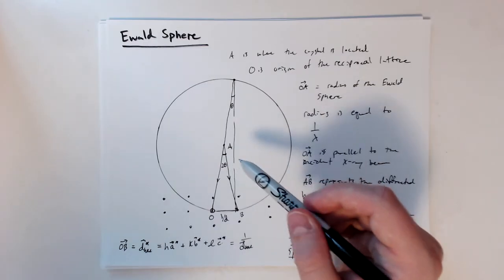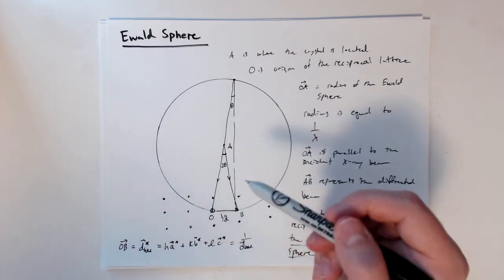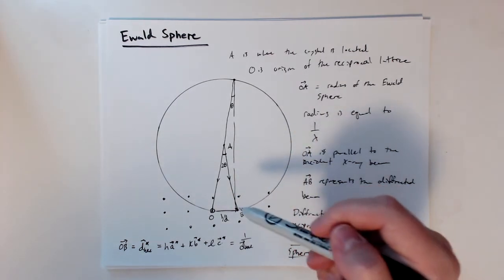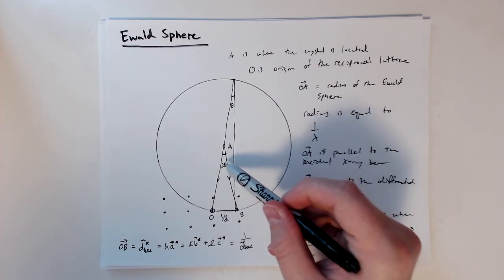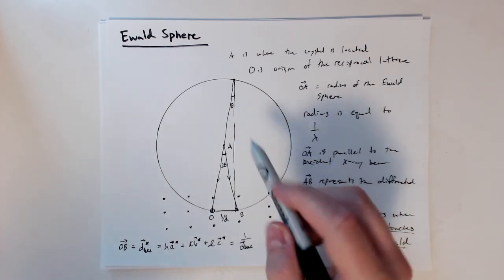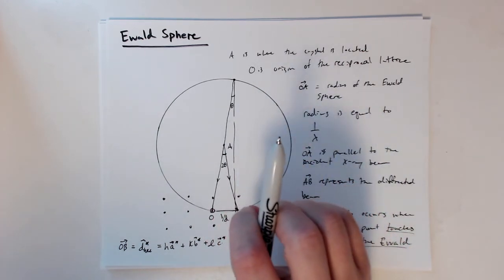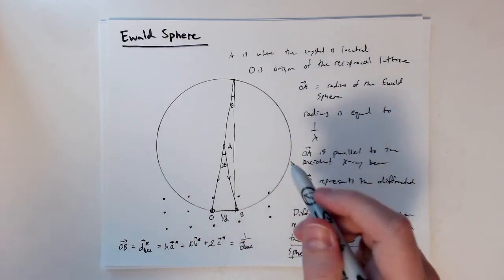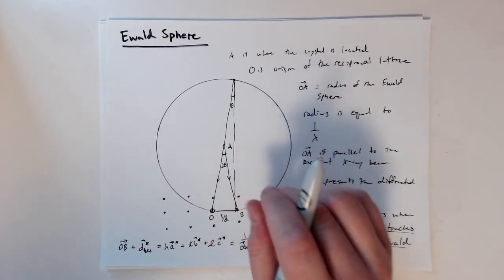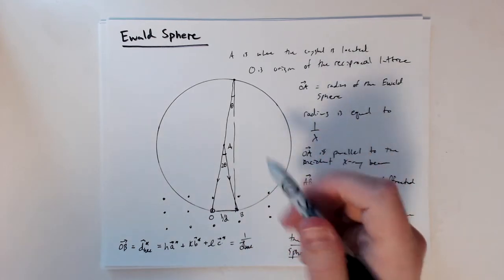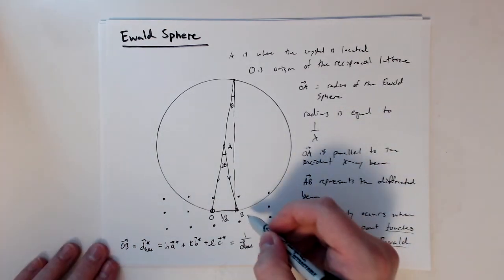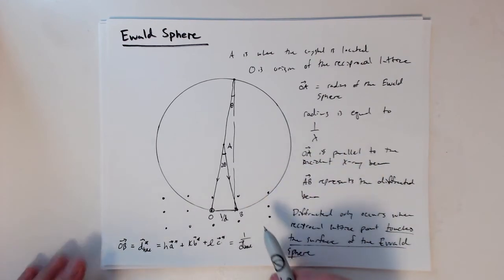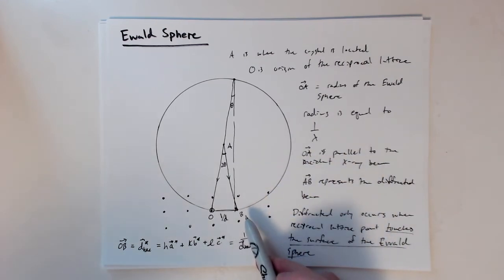And so if we want to think of this in terms of Bragg's law or an X-ray diffraction experiment, we're often scanning the angle theta. Changing that angle is what allows us to determine visually, using this Ewald sphere construction, whether diffraction occurs, by essentially whether it touches the surface. So basically, B, since it's on the surface of the Ewald sphere, satisfies Bragg conditions according to Bragg's law.